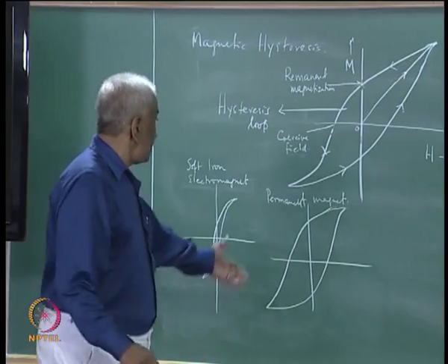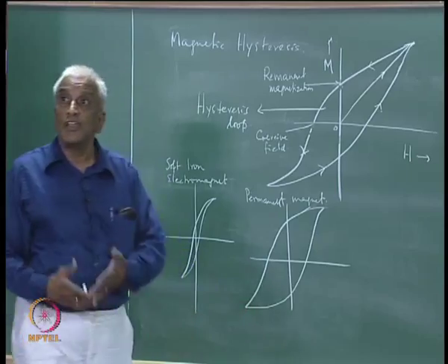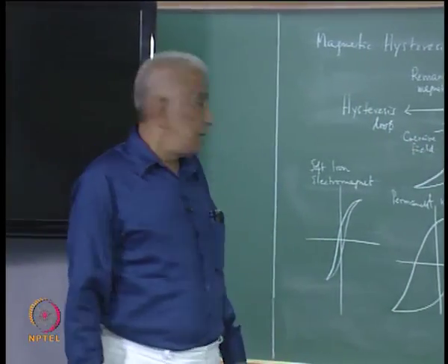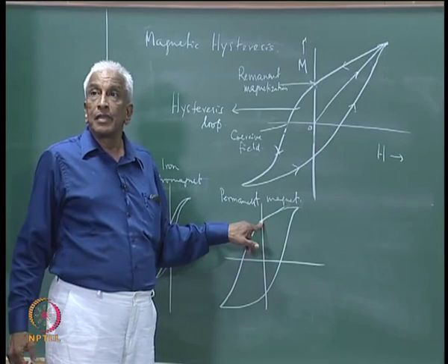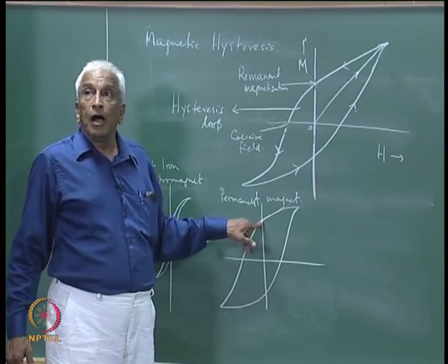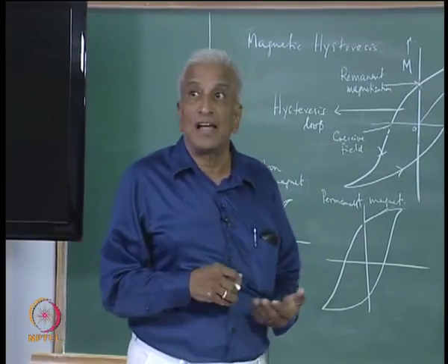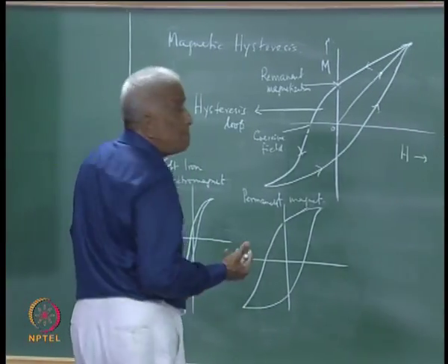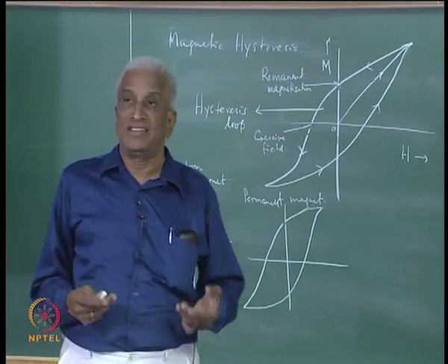So, you can see that the area of the BH loop or MH loop is correspondingly large. Now, how do you produce such a high remnant field? This is achieved by precipitating impurities like carbon atoms, which impede the motion of the so-called magnetic domains.